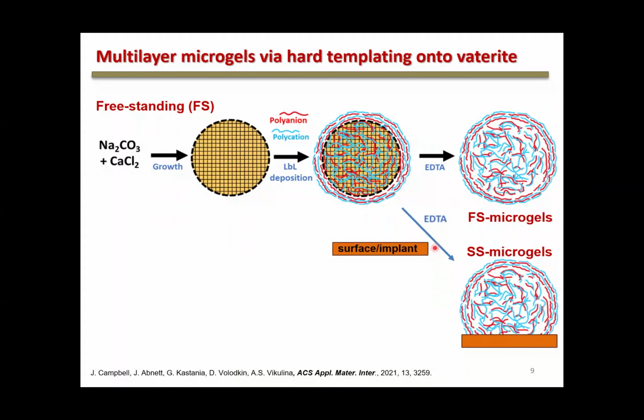So what will happen if in the last step, when you get rid of the core, you do it not in the bulk, but in the presence of a solid surface, like an implant, for instance. In this case, some particles, all of them, or maybe none of them, it depends, I'll show you this later on, may stick to the surface. And now they will not be freestanding, FS, but SS, surface supported particles. So they will stick to the surface and you can hardly get rid of them.